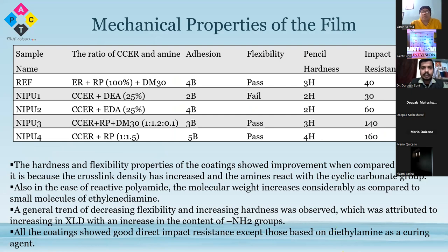Also in this study, the reaction was performed with different curing agents like ethylene diamine and reactive polyamide. So this was the reference sample in which the pure epoxy resin without cyclocarbonation was used with the reactive polyamide and DM30 as an adhesion promoter. The adhesion obtained was 4B. And when the cyclocarbonated epoxy resin was cured with a reactive polyamide, the adhesion was 5B.